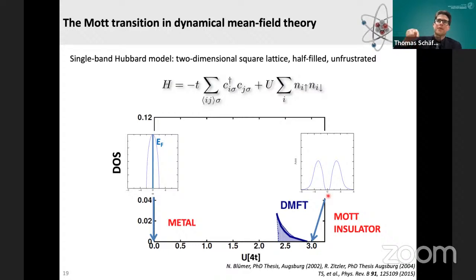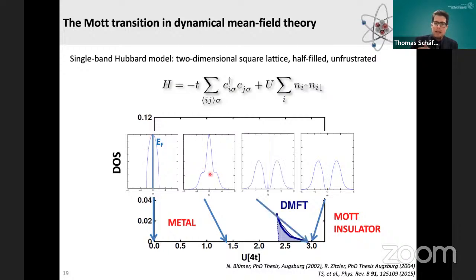However, this insulator does not stem from the crystal structure, so from band theory, but because the Coulomb interaction is so large that two electrons do not want to sit on the same lattice site anymore. So you can think of it like this: you can never conduct, because for conducting an electron in a half-filled system, where you have an average occupation of one electron per lattice site, you always have to create a double occupation of your lattice sites. And this is now forbidden, so you have a gap. If we go to intermediate couplings, we get features of both. So we get a so-called quasi-particle peak here in the middle, and the onset of these two Hubbard subbands. This quasi-particle peak vanishes at this transition, and the Hubbard subbands really split into two.